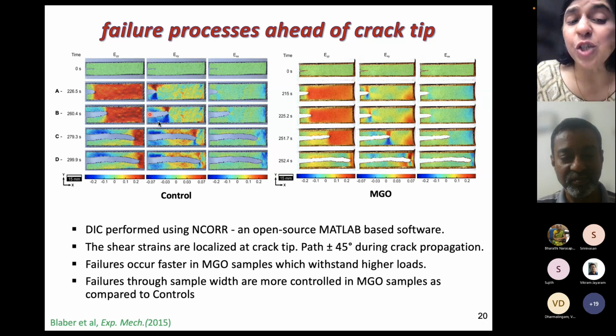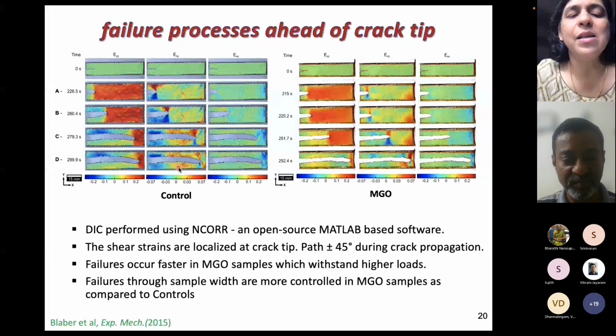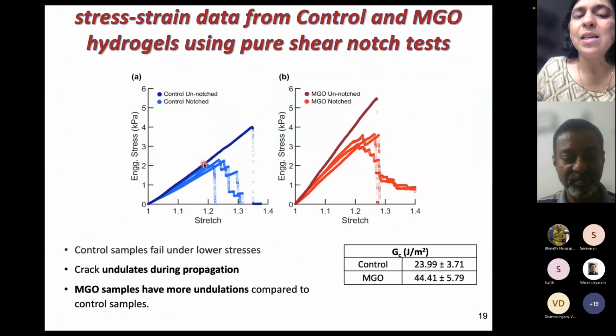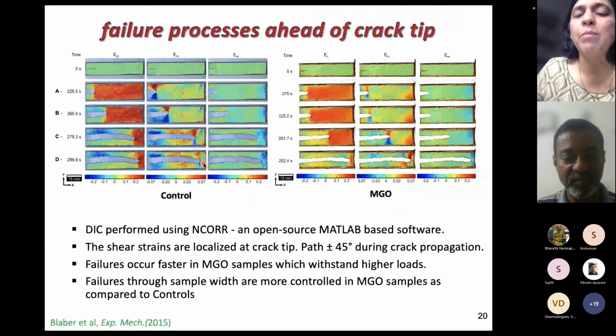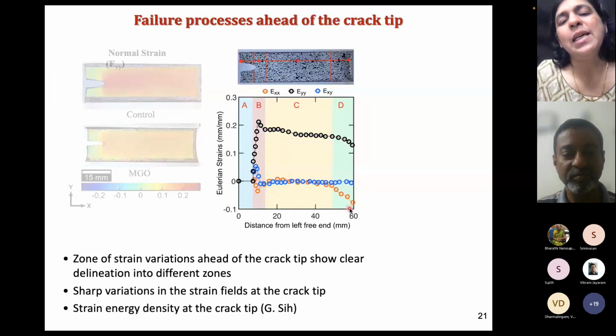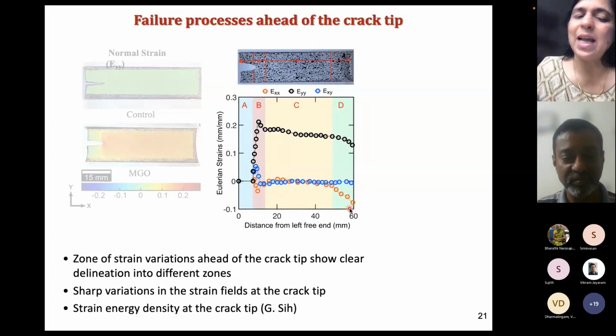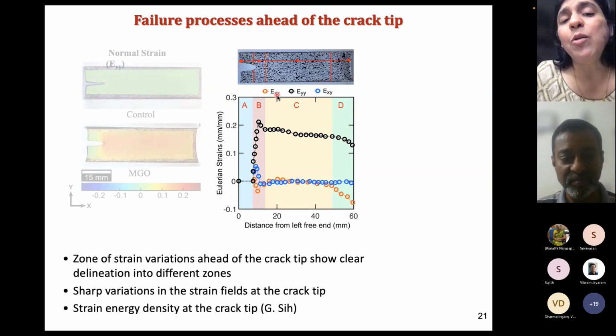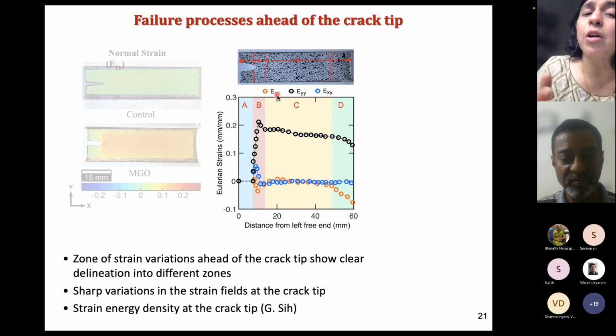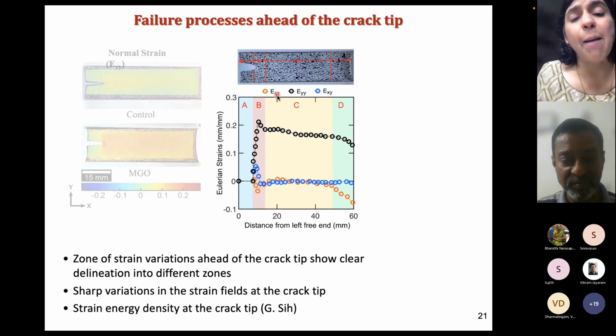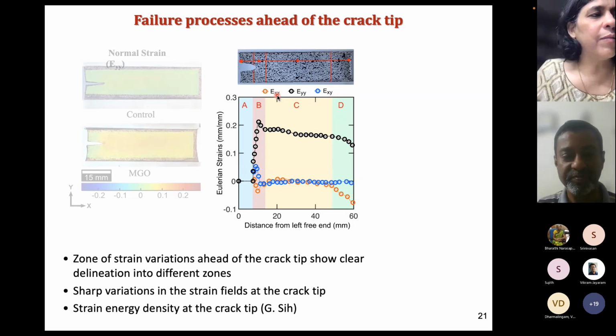So at which point does it stop? As we are getting almost beyond the 50% mark, you will start seeing that this domain D starts looking more and more thin and short. And that is when we'll have to essentially not take anything further to model. But this A by W, the rules of how long should the crack be inside the sample, that is also something that is followed from literature. Does that make sense, Raghu? Yeah, fine. Thank you. So I'll just continue.